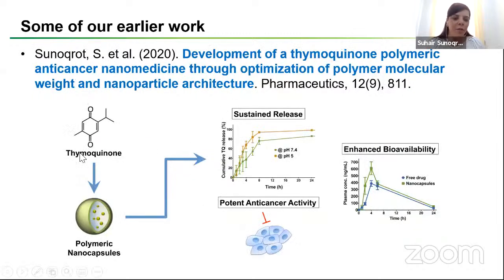And then we also worked, this was actually the effort of one of my undergraduate students, where we took thymoquinone. It's not exactly a polyphenol, but it's also another potent natural compound from Nigella sativa, the black seed. And we encapsulated it into either nanospheres, like conventional nanoparticles, or oil-cored nanocapsules. And we found that the nanocapsule formulation performed much better, and it showed more sustained release and potent anti-cancer activity, especially against colorectal cancer cells and pancreatic cancer cells. And also, when we tested it in mice in vivo, it showed much better bioavailability after oral absorption.